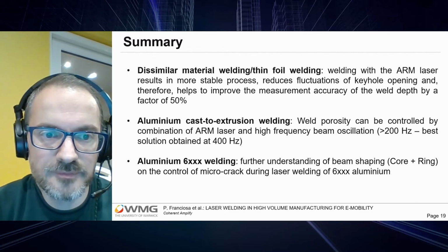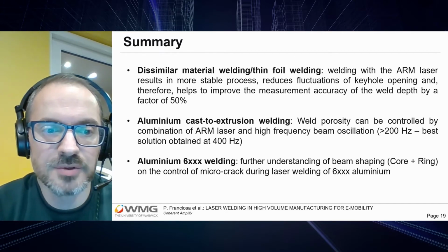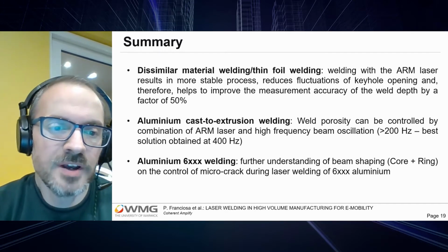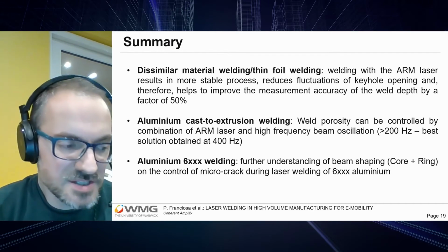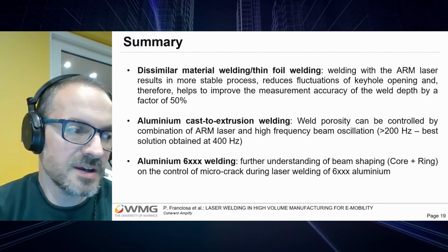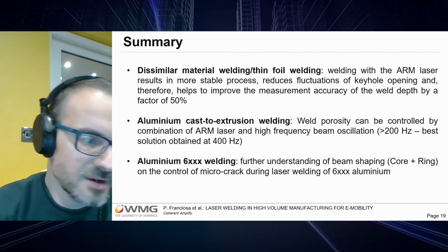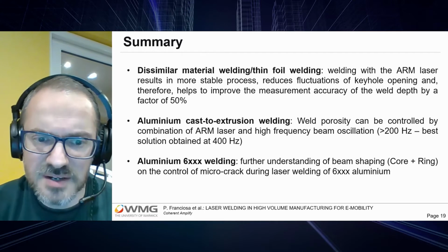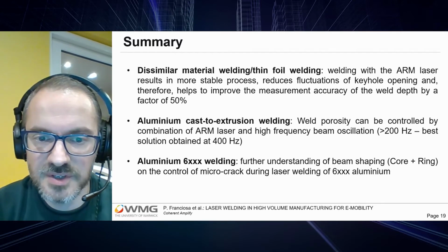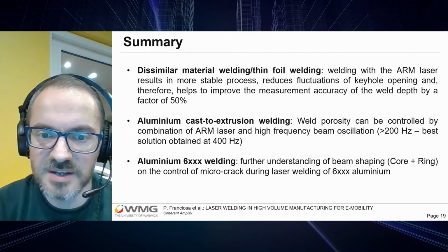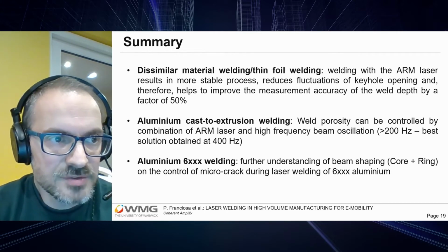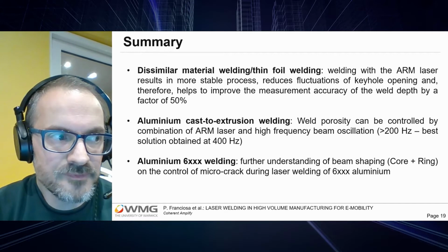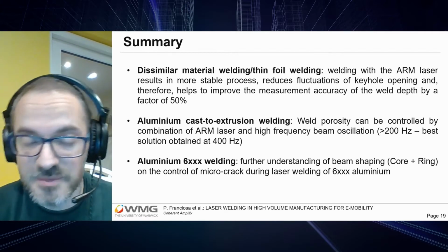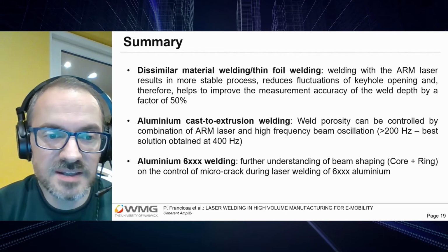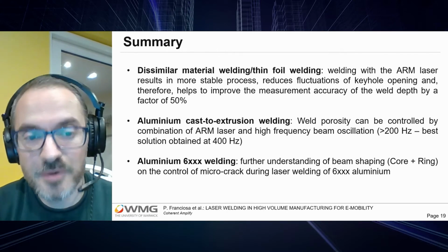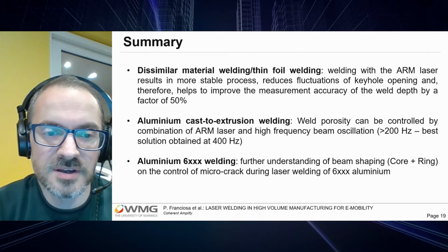The second application was about the welding of aluminum 6000 series. The challenge is about controlling the crack level, either macro crack or micro crack, without filler wire. I want to stress again that we didn't use any filler wire for those experiments. And the result also confirmed that there is a 10 to 15% improvement of the joint strength if you optimize properly the power level on the ring.